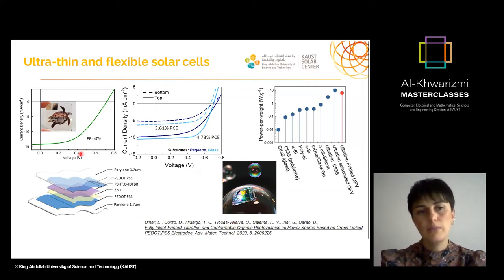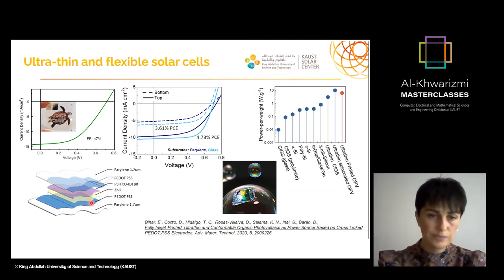So with the ink we developed in the first part I showed you, which was P3HT-based, we decided to move on to completely conformable and ultra-flexible substrates, and we got rid of our whole ITO glass, etc. And we developed another PEDOT:PSS here that can sit on it as an electrode. And we fully inkjet printed, in this case, this photovoltaic device, as you see, that is sitting on a soap bubble. So it's extremely light, yet it is still very effective.